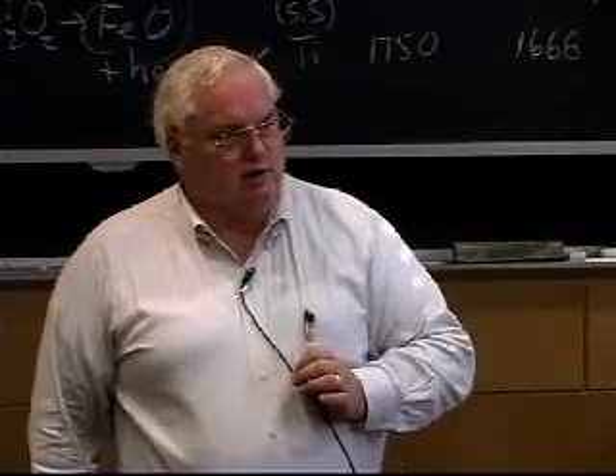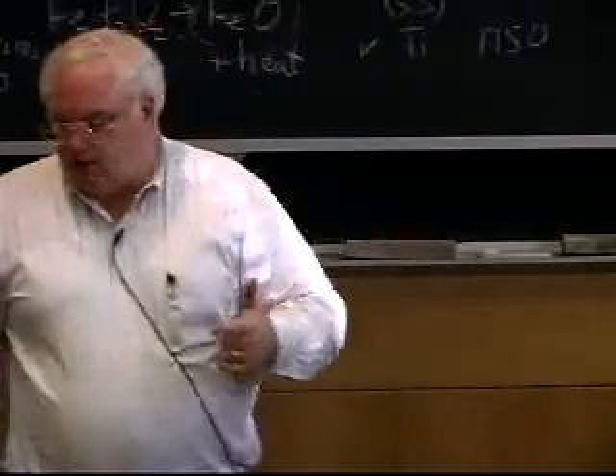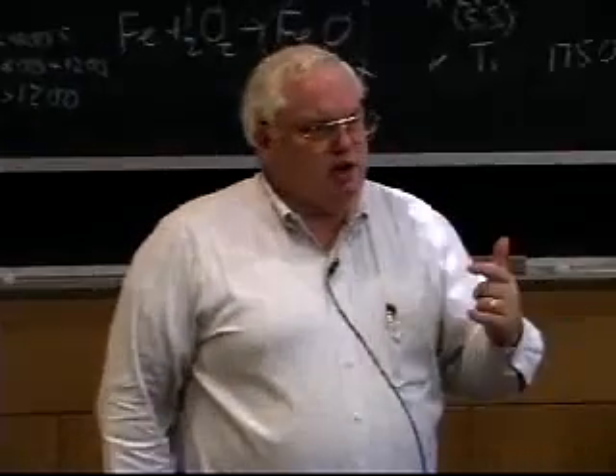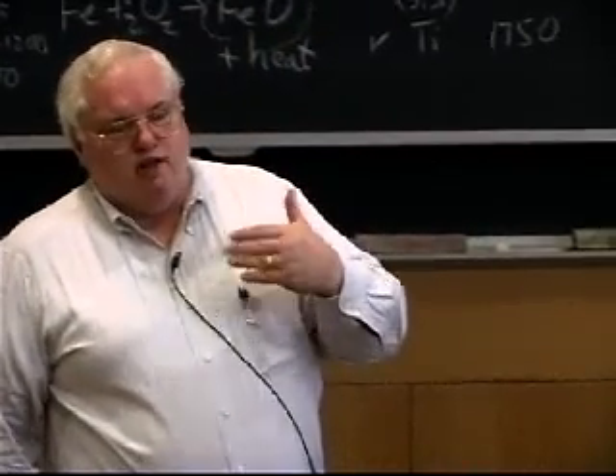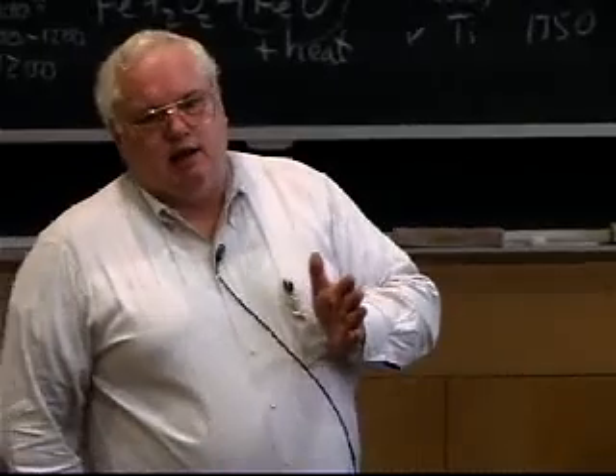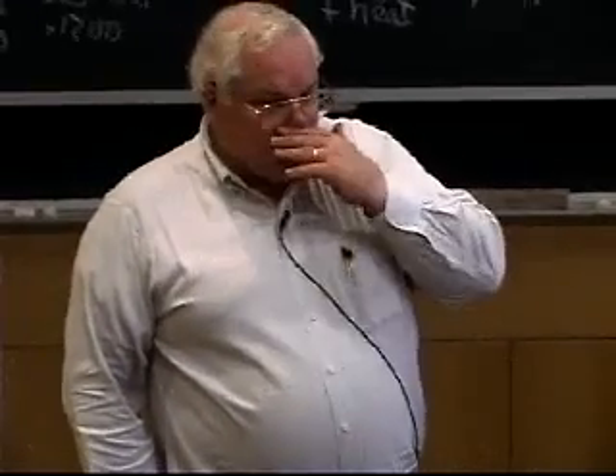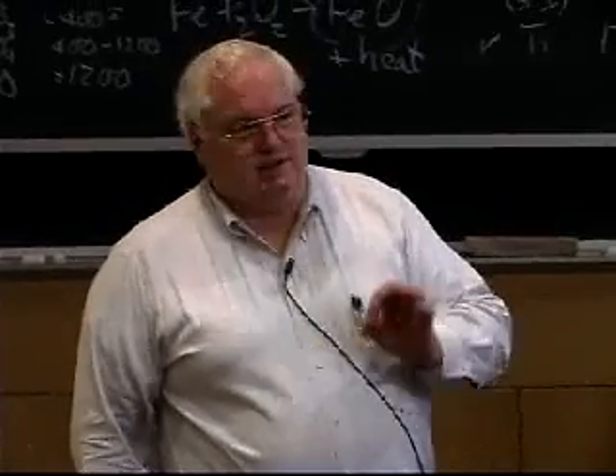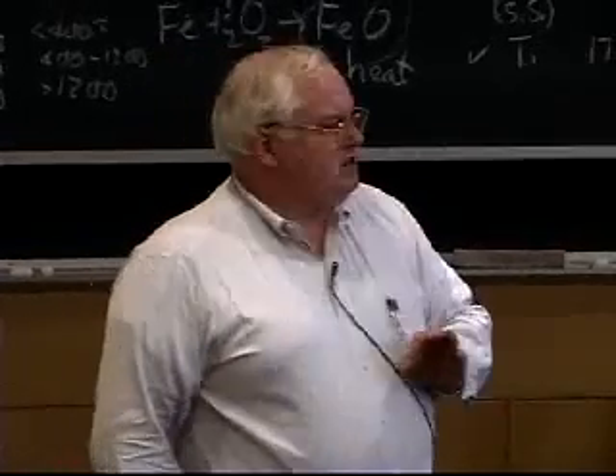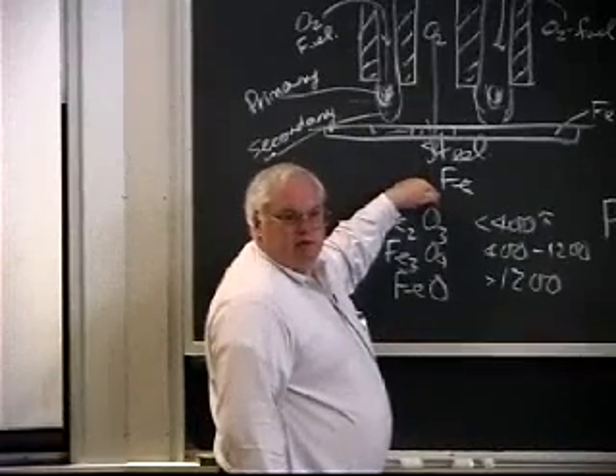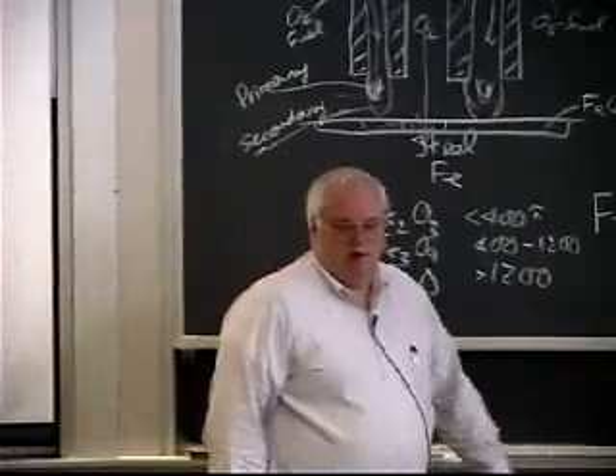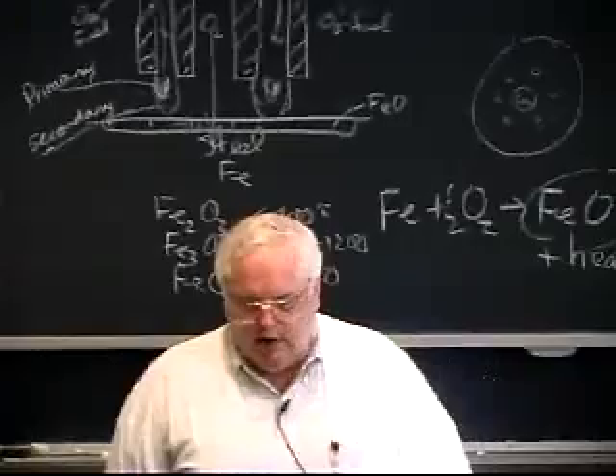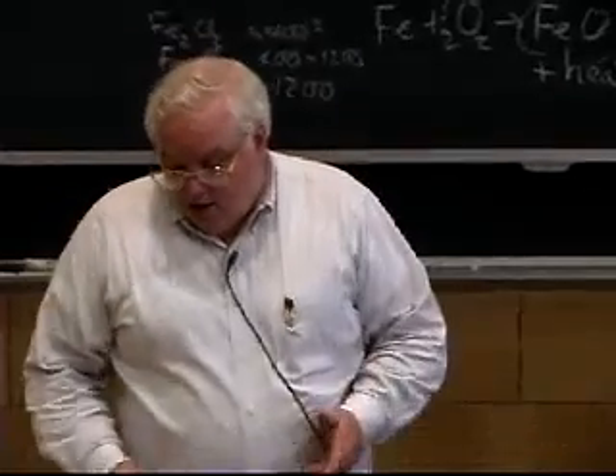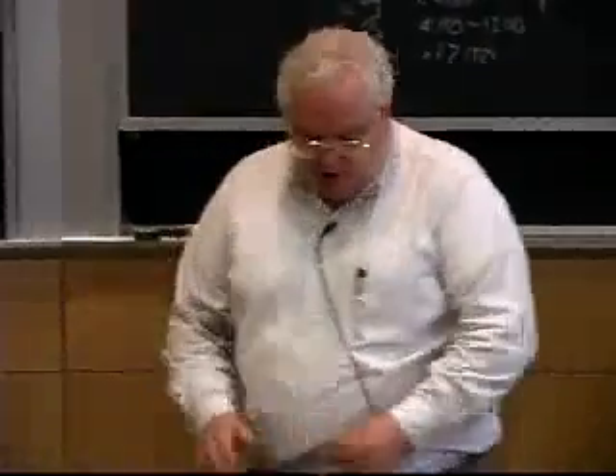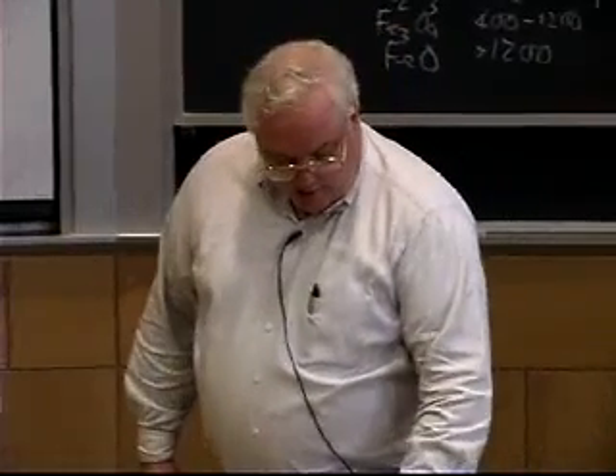an effective heat intensity. And if I look at my heat effective zone sizes and travel speeds and everything else, the effective heat intensity is several times 10 to the fourth and approaching 10 to the fifth watts per square centimeter as an effective surface heat intensity. But it's not really a surface heat intensity because I'm really blowing my fuel down beneath the surface, right? But nonetheless, if I look at these other parameters, it's a very, very high heat flux. The problem is it is actually limited by some other things.